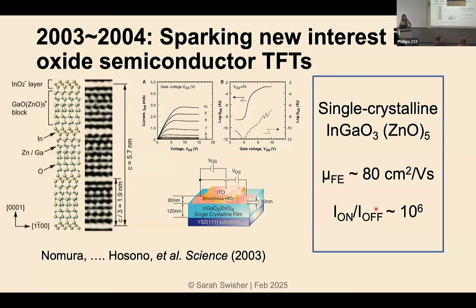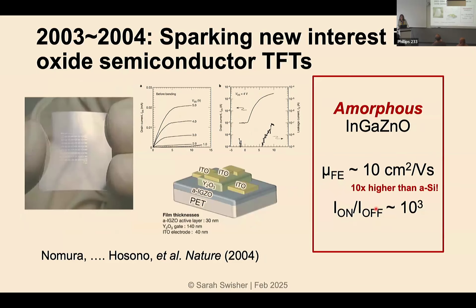And this was an order of magnitude or two better than what had been achieved with most zinc oxide and other oxide work in the past. So this was really a game changer. And then the next year, the same group came out with an amorphous indium gallium zinc oxide material process. And they showed that when you make these films amorphous, you actually maintain a lot of the transport.